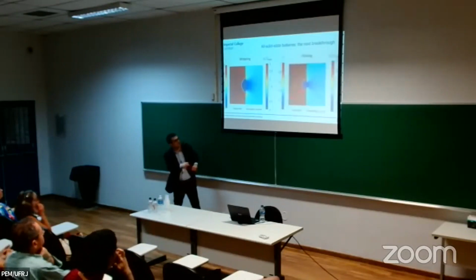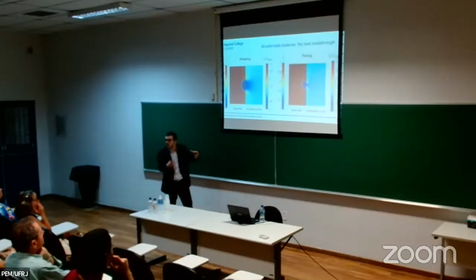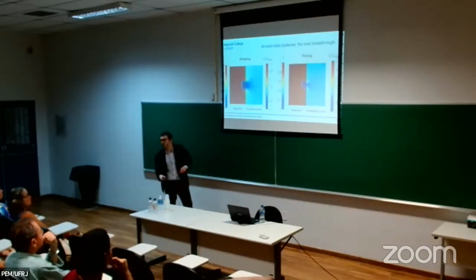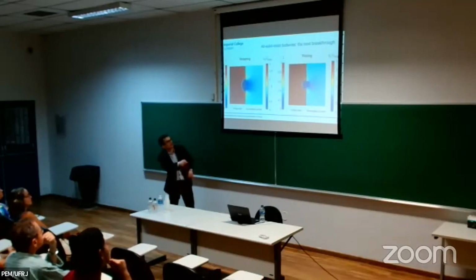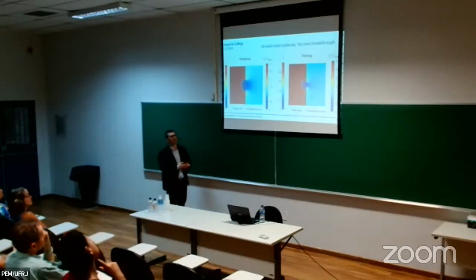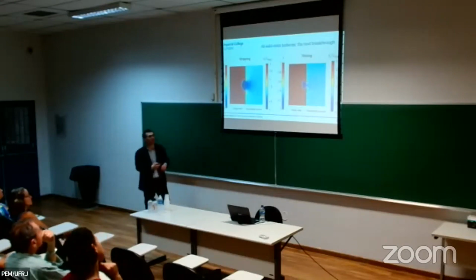And this is what you see when you get plating. Again, you see how the void starts shrinking and how eventually it separates itself from the interface. So it's exactly what we're seeing qualitatively, at least on the experiments. And again, we can see how those hotspots eventually disappear with the plating cycle. So we replicate the trends.